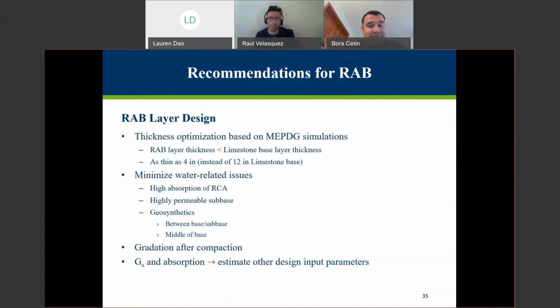You can get the stiffness performance of the material, the overall pavement performance prediction, by using 4 inches of some of these materials instead of using 12-inch limestone base. Of course, this is just a simulation, so this needs to be verified in a field study, but based on this pavement ME analysis, you can decrease the thickness of the base layer significantly if you use RCA material compared to using freshly crushed quarry aggregate base materials.